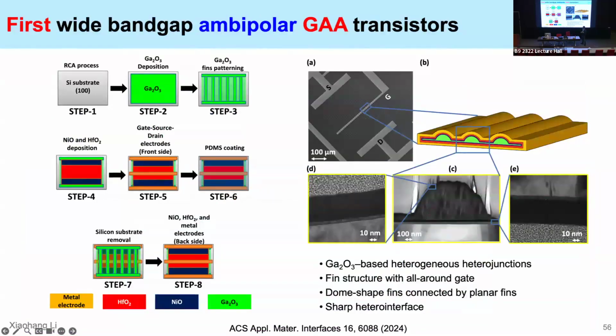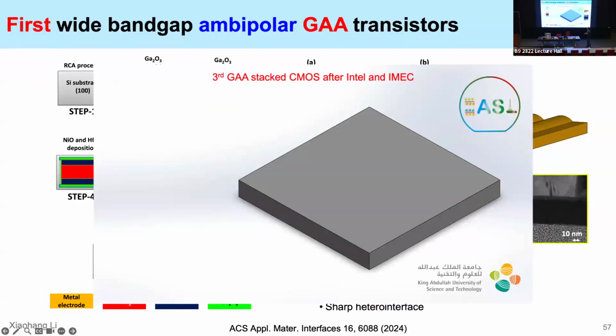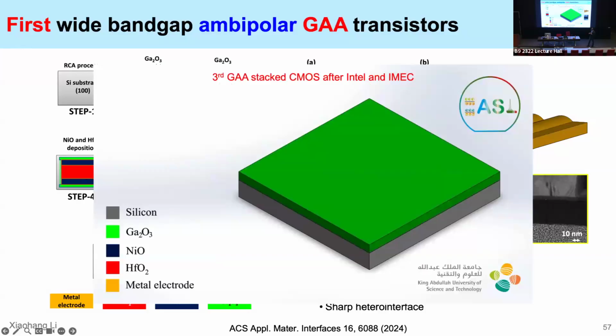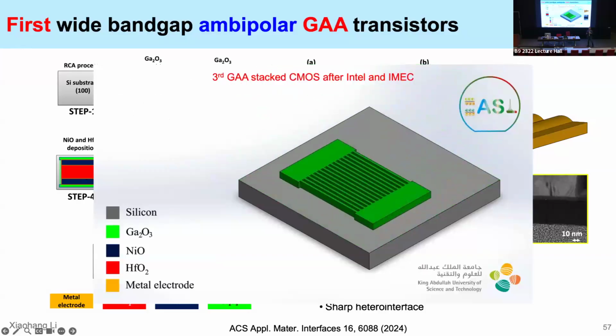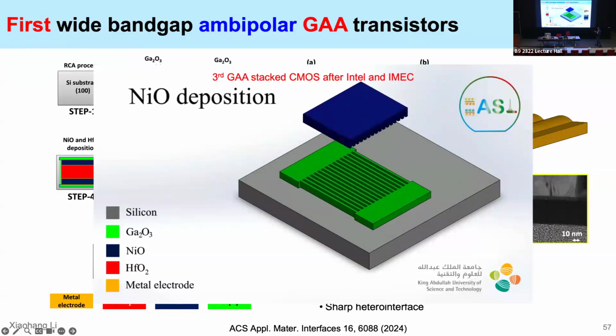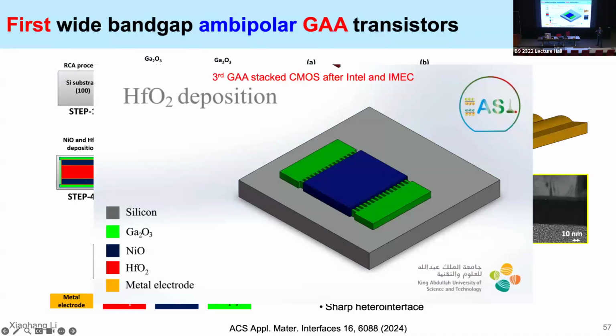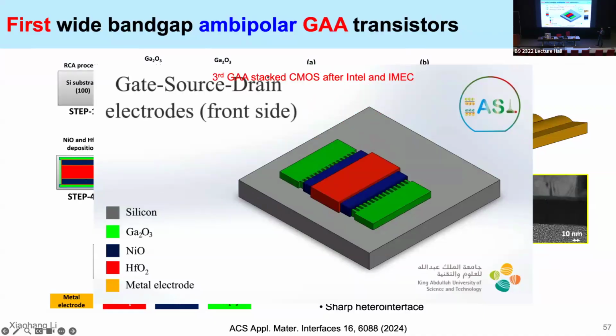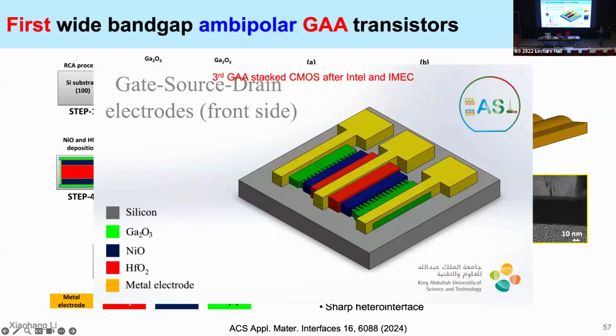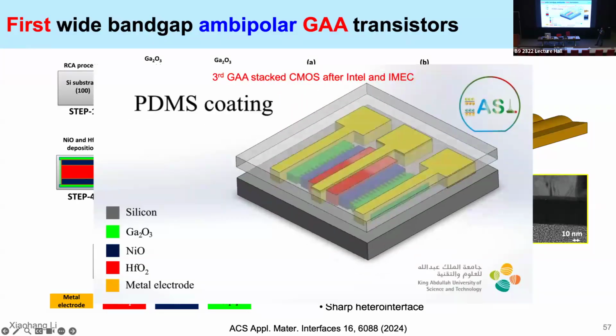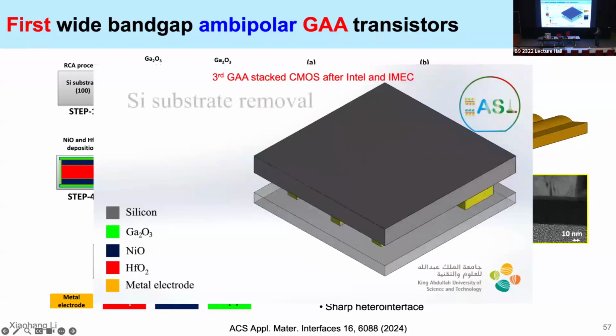So this is the fabrication process of our ambipolar transistor CMOS. And here is a video. So we start from a silicon substrate, deposit gallium oxide, and then pattern that, and then we deposit nickel oxide. The nickel oxide here is to provide holes because gallium oxide is primarily an N-type material. And then we deposit hafnium oxide as a dielectric and the metal as source, drain, and gate.